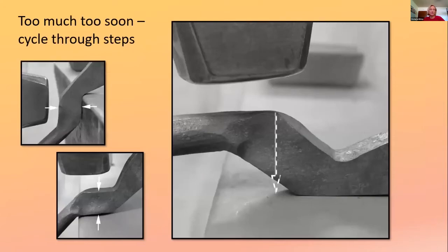The other thing that can go wrong is you end up over forging when you're dressing the boss. So even though our hit is the right direction and everything's nice and parallel, this ended up way too thin. Now there's nothing to support it when you try to crisp up this corner and it's just going to end up flat. You hit here, this middle is just going to squish down. This is a do-over. This isn't going to be corrected at this point, which is fine. All practice is good practice.